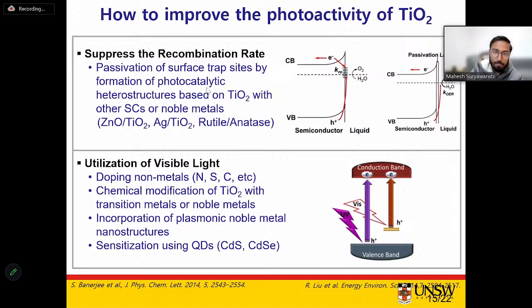As I said again, the band gap of this one, by putting these different heterostructures, will not improve. So what we need to do is utilize the visible range of the sun spectrum, and that can only be done by either doping with non-metals, which reduces the band gap of this TiO2, which is nothing but nitrogen, sulfur, and carbon, or we can do chemical modification of TiO2 with tungsten or the noble metals, such as silver and gold, because silver and gold are plasmonic, noble metals which absorb in the visible region, or the interesting one, which is sensitization with quantum dots, either cadmium sulfide, cadmium selenide, or some other non-toxic elements.